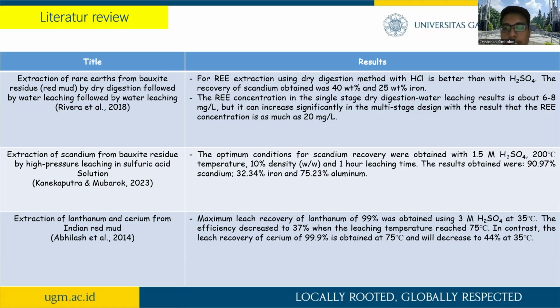The optimum conditions for scandium recovery were obtained with 1.5 molar sulfuric acid at 200 Celsius temperature, 10% density, and 1 hour leaching time. The results obtained were 90.97% scandium, 32.34% iron, and 75.23% aluminum. The third literature, extraction of lanthanum and cerium from Indian red mud by Abhilash et al.